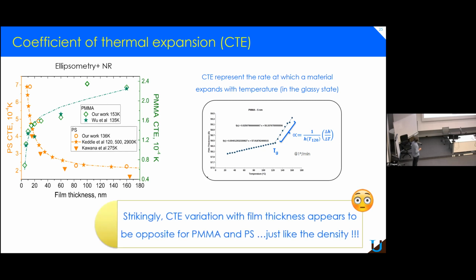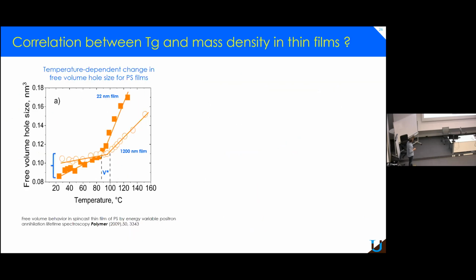So what you see here is that the CTE variation with the film thickness appears to be opposite for PMMA and PS, exactly as the density for PS and PMMA is opposite. And they are varying in the very same manner. So obviously, CTE is not free volume. It's related, but it's not really the measure of the free volume.